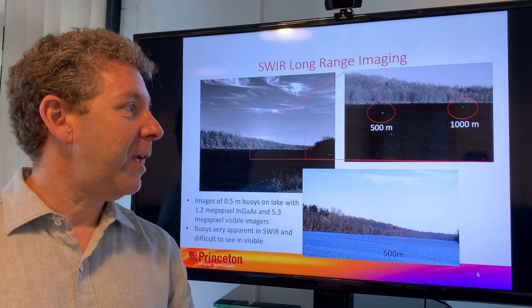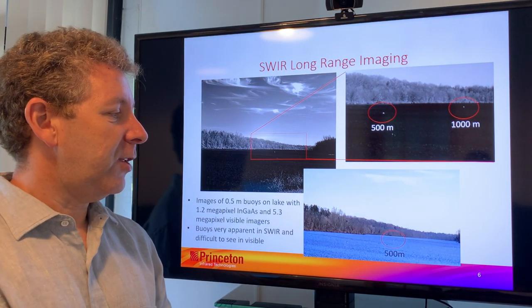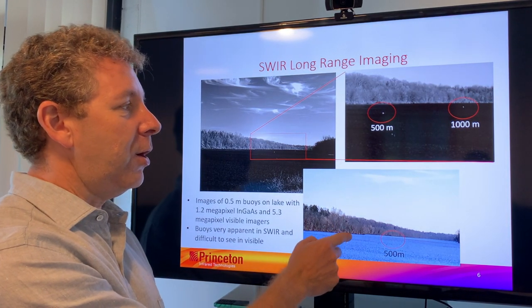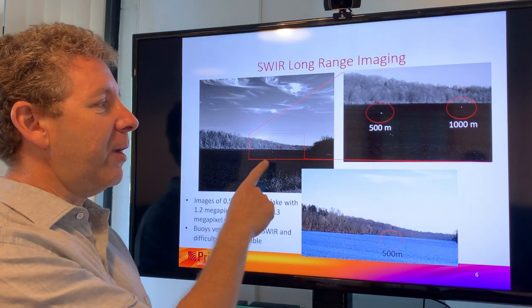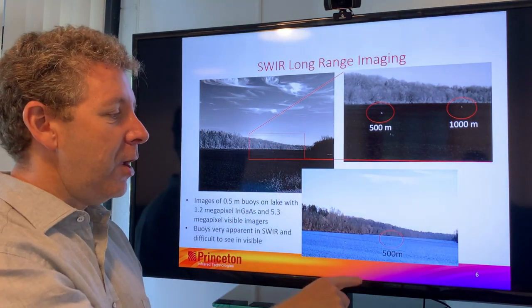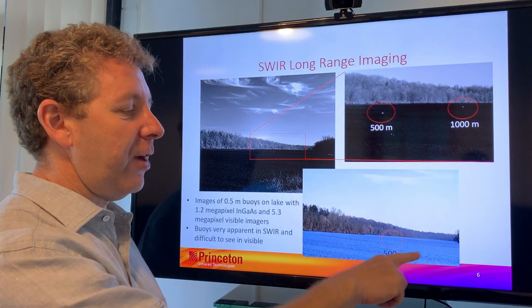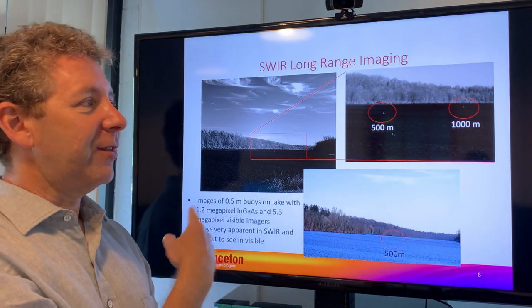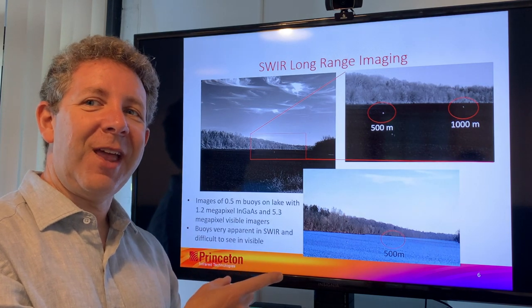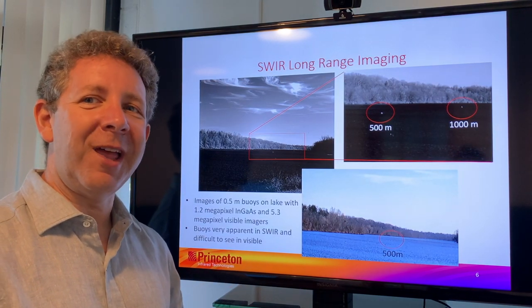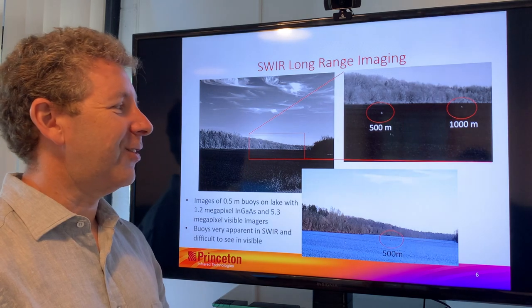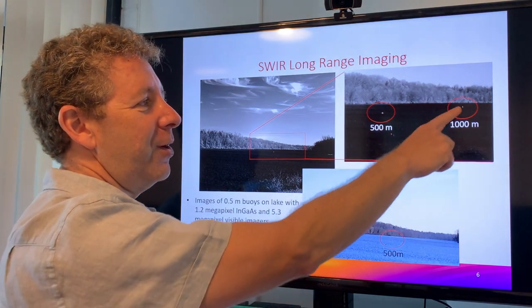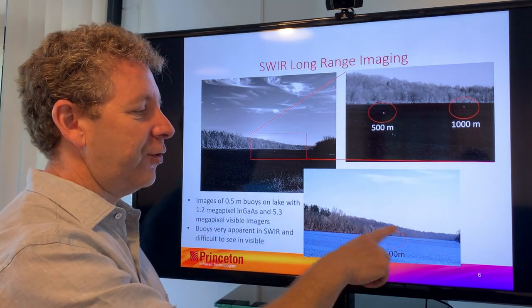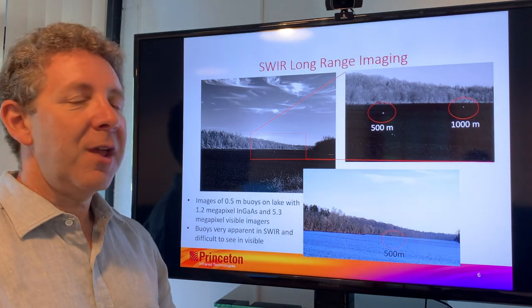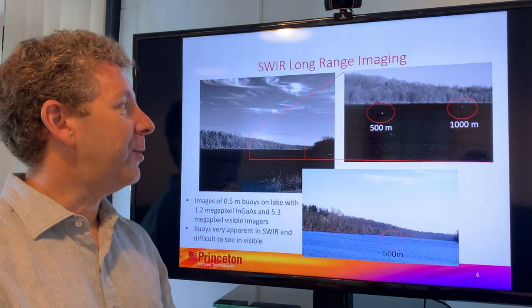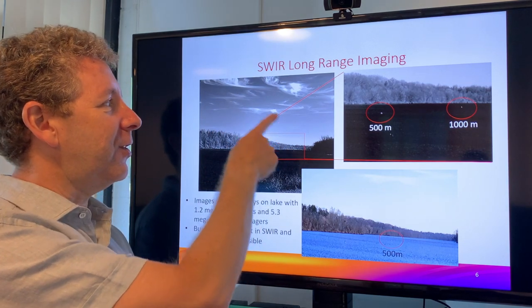Better atmospheric penetration. This is a 5.3 megapixel camera here versus a 1.2 megapixel shortwave infrared camera here. You can't even make out the 1,000 meter buoy. This is Lake Carnegie, so we actually know exactly how far the buoys are because this is a rowing lake. That's the 500 meter and the 1,000 meter buoy, and it is just lost. And it's due to the atmospheric haze, and we're only talking about a small amount of atmospheric haze. This is a pretty clear day, as you can see. There aren't that many clouds seen here.